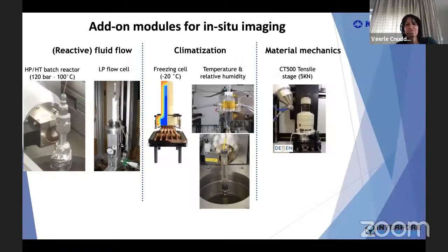We have invested in add-on modules for in situ imaging, to do tests on reactive fluid flow, climatization where we can control temperature and relative humidity. We have freezing cells, and also a commercial system where we can do compressive testing, tensile testing, control of temperature, and capillary water uptake.